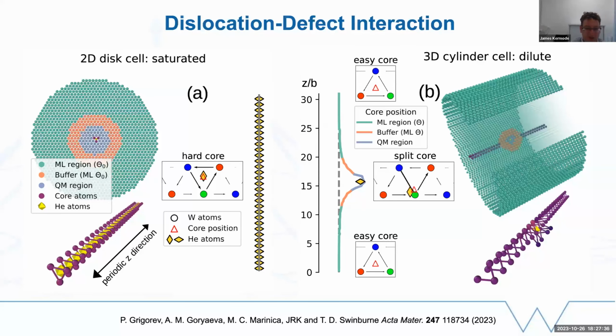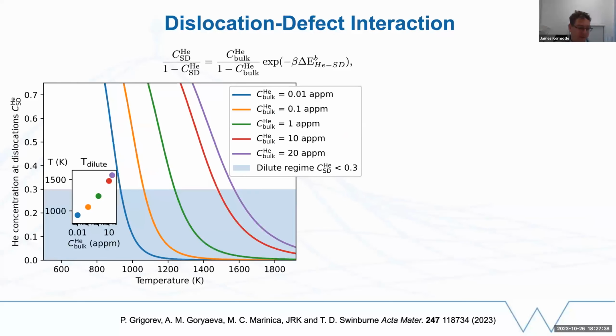What Vector was then able to do was put in more and more helium into the dislocation cores and look at the effects that has, and effectively extract rules that could then be used to inform larger scale simulations. So looking how different temperatures, energy barriers are changing and what that means for the resulting helium concentration. So it can really make useful predictions at larger scales.